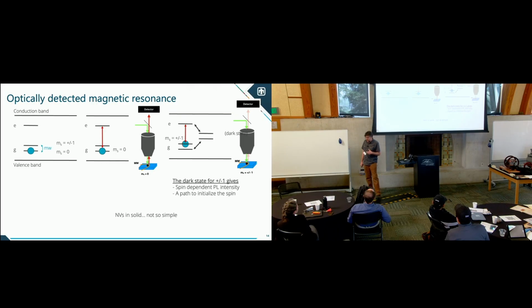So now in our band gap, and I'm going to ignore the excited spin states for a second, but now within the band gap with this ground state, we have a splitting between the ms equals 0 and the ms equals plus or minus 1. And we can actually drive this with a microwave resonance. All right, at zero field, it's 2.87 gigahertz. In field, it's higher. Now, if it's in the ms equals 0 state, you can excite it, and it will just come right back down. All right, and you get a photon out as you excite it.